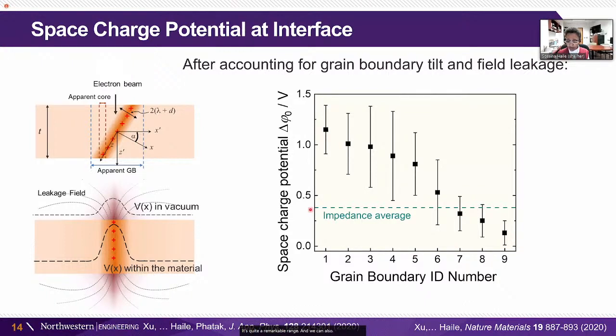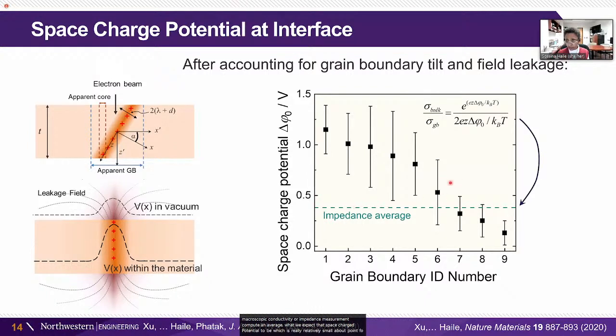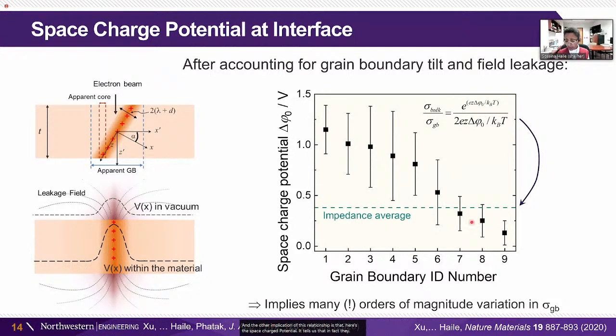And we can also, from our macroscopic conductivity or impedance measurement, compute an average, what we expect that space charge potential to be, which is relatively small, about 0.4 volts. The way that is calculated is to use this expression here. It's a derived expression. And the other implication of this relationship is that here's the space charge potential. It tells us that, in fact, there would be many orders of magnitude of variation in transport across each one of these individual grain boundaries. So, whenever you look at a small enough scale, you see variations. And here, this variation would be orders of magnitude. And it tells us that the transport really must avoid some of those high impedance interfaces and travel along the more conductive grain boundaries.